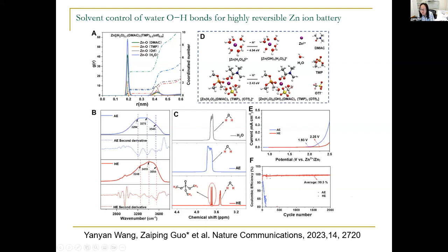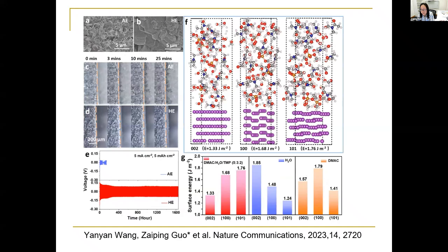And the zinc copper asymmetric cell can achieve much better coulombic efficiency, 99.5%. Also, we found that the zinc deposition behavior changed in this electrolyte compared to the normal aqueous electrolyte. The surface energy along the 002 plane is the lowest, indicating it is the preferred orientation. So therefore, the zinc deposition has 002 plane orientated deposition. In this way, we can achieve a dendrite-free zinc anode in this hybrid electrolyte. So the zinc symmetric cell has very good reversibility.